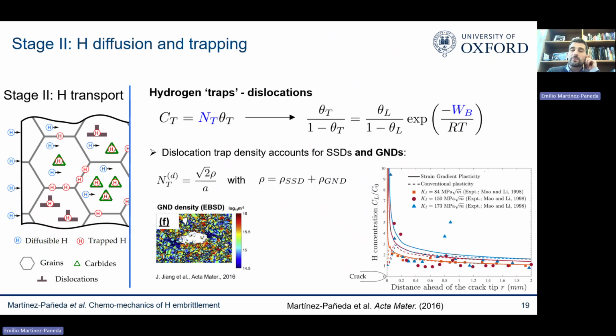One thing I will say about these traps is that there's a coupling with mechanics, because the trap density doesn't really change. The number of grain boundaries doesn't change with mechanical straining typically. However, dislocation traps will change. The number of dislocations is related to dislocation density, which is related to plastic strains, but also to plastic strain gradients.